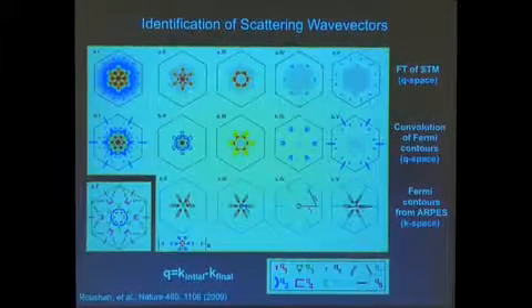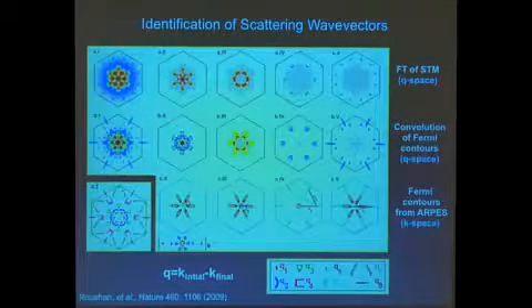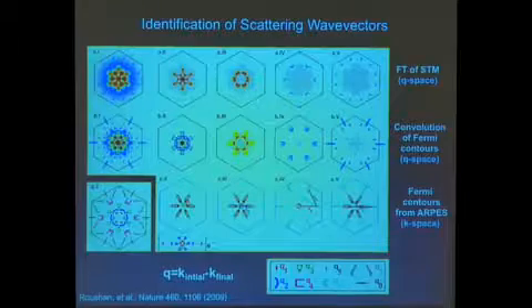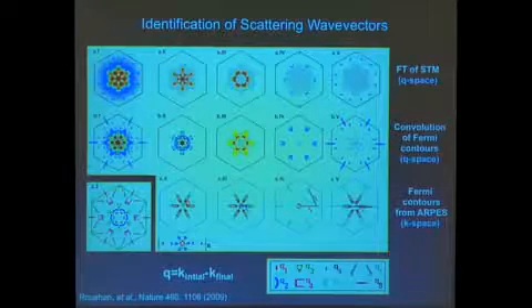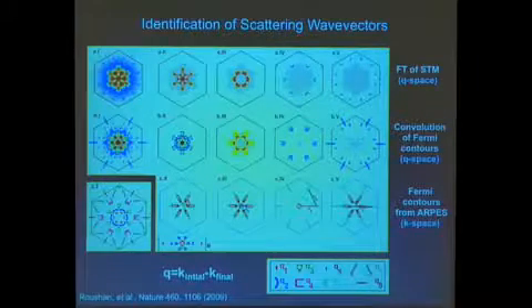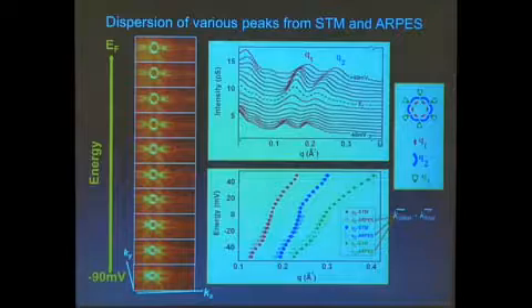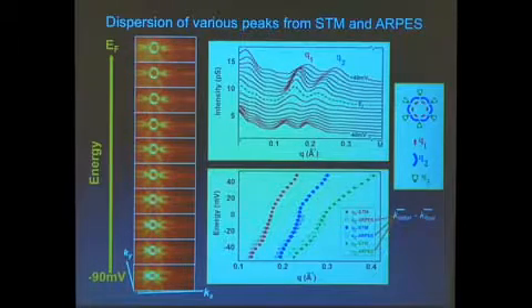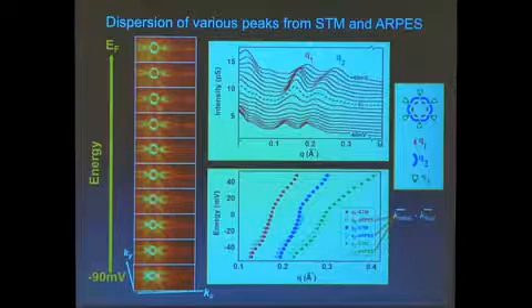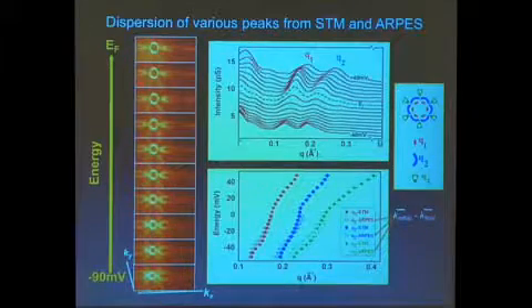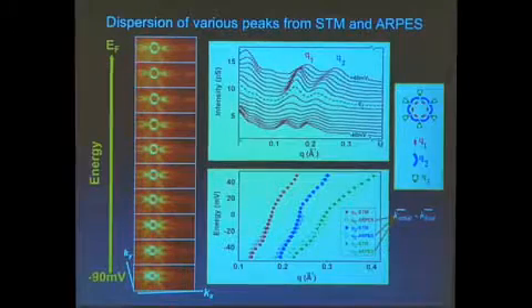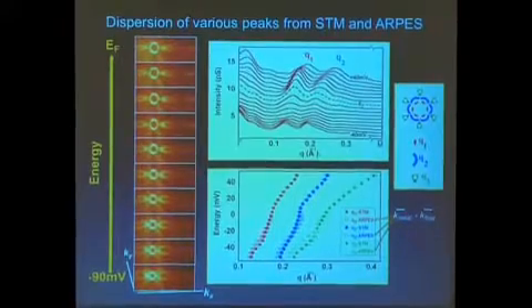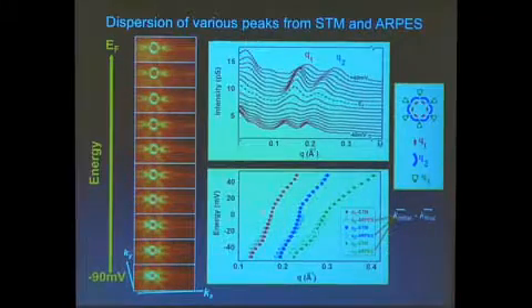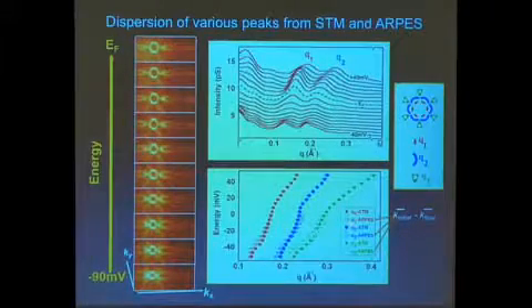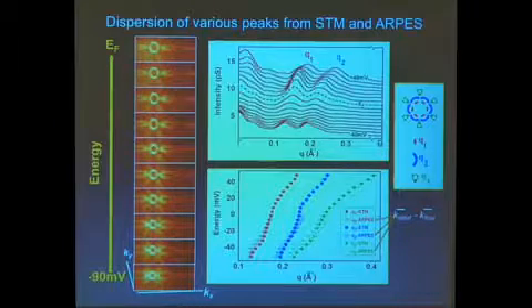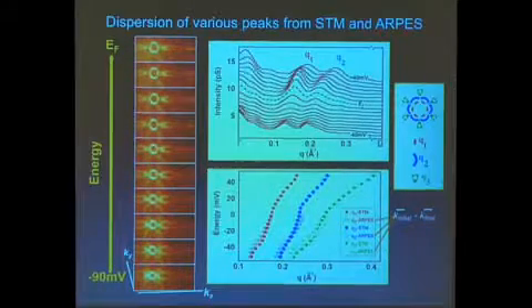Okay? Now, you can imagine situations in which I believe you have to break time reversal symmetry. I think there is no other way. Okay? So I won't bore you with the details of trying to understand this beautiful data based on all the allowed scattering and the disallowed one. I just want to make one point, which is that we can do this in very high precision. Namely, we can look at the measurement of the electronic Fermi surface as a function of energy, and using this model in which we take into account the spin texture, we can map basically the simulation to the experimental STM data with very high degree of accuracy for the places below the chemical potential, which there is information from angle resolved photoemission. So this is the comparison between model and the experimental data.